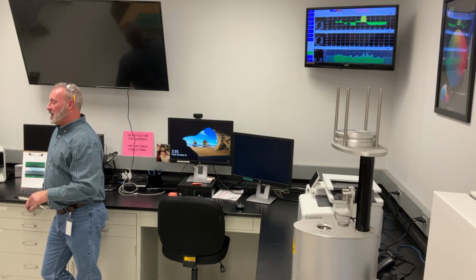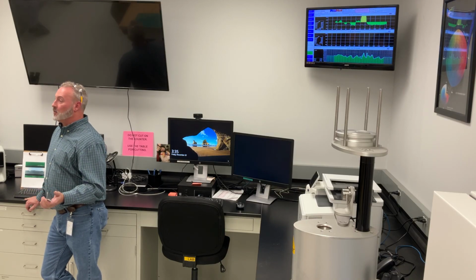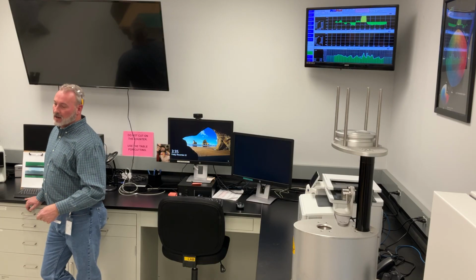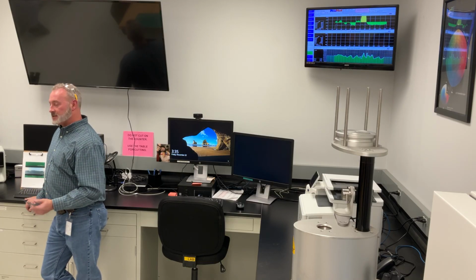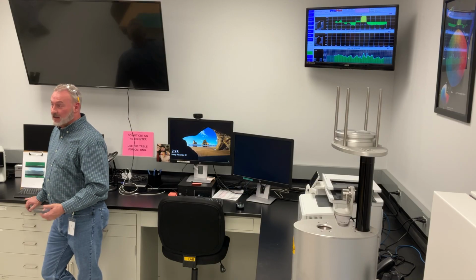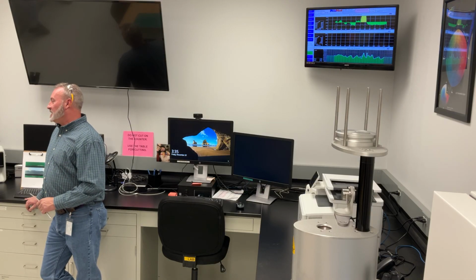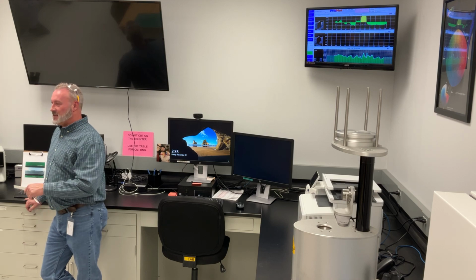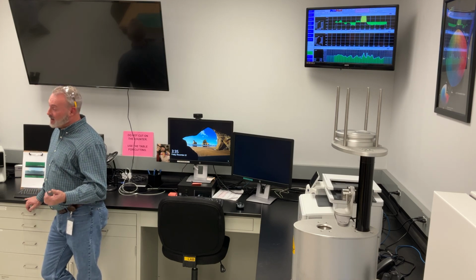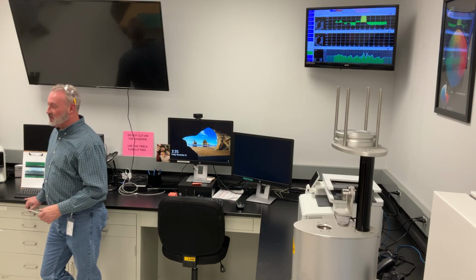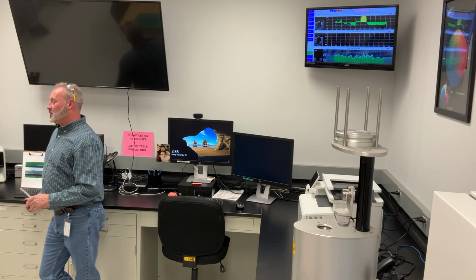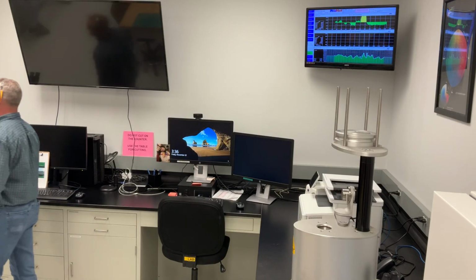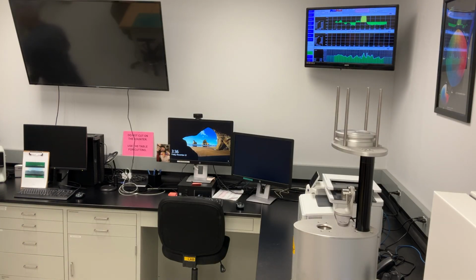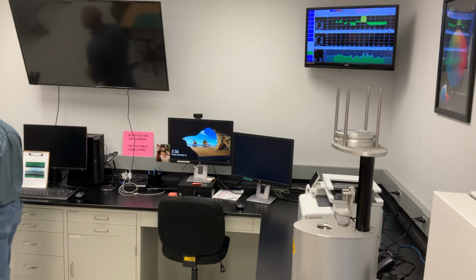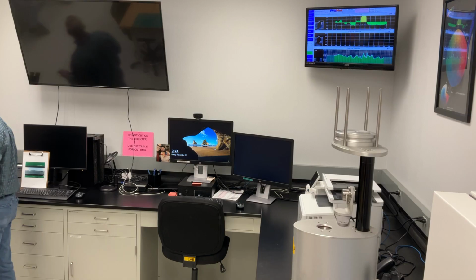There was a new individual in the lab at the time, and we thought, okay, he didn't get a good weld. We had one of the other guys weld it, we put it in there, pulled it, got the same numbers. We sent that report out. Immediately, Brandon Burton, who is TIA for Cedar City, was on the phone. Kevin, what the hell are you doing? This stuff passed. So we kept looking at it. We went back and welded some more product, and what was happening was it was actually slipping in these grips, so it wasn't holding in there tight. These are fine-tuned adjustments that you can tune in a little bit more. We did that, and we got past it.